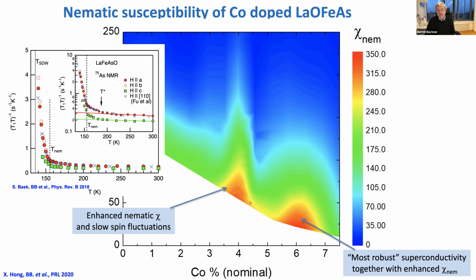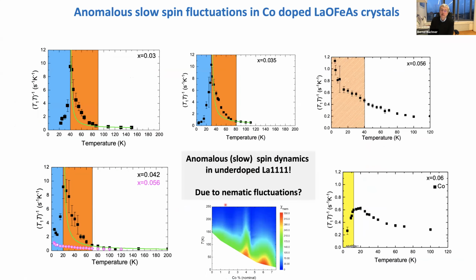This means that we have a very interesting region here. We have these very slow nematic fluctuations, which are coupled to the spins, and somehow this should also show up in unusual spin behavior. And that's also what we see. What I've plotted here is also measured on these single crystals, the NMR relaxation rate on compounds where you still have the magnetic order. You see the strong peak, and then this magnetic order disappears. Then you observe a very unusual behavior of 1/T1T, plotted here for one of these underdoped compounds, which is hardly or not really superconducting.